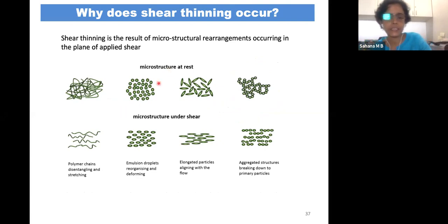Shear thinning is a result of microstructural rearrangement occurring in the plane of the applied shear. This can happen in binders, which are basically single-chain materials, and it can also happen in carbon blacks, which are small particles of around 20 to 30 nanometers. So now this is the microstructure at rest. When we don't apply a shear, this is how the microstructure of the material looks.